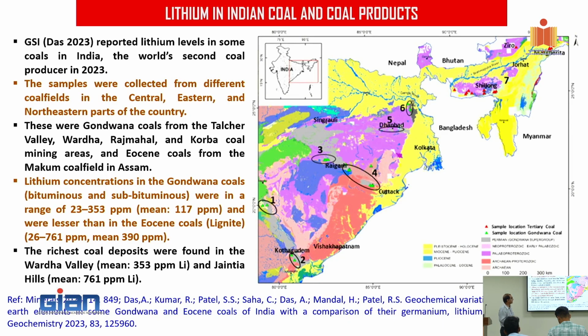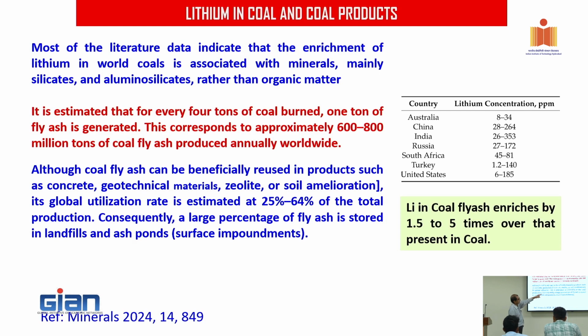Now, very recently, it has come in the public domain, by our friends in CSIR labs, that some of the coals in eastern part of India do contain lithium, and that lithium content is also very attractive. If you see here, the lithium in the coal of Australia is 8 to 34, China is 28 to 264, India is 26 to 353, not bad. Russia is 27 to 172, South Africa is like this. So this is in the